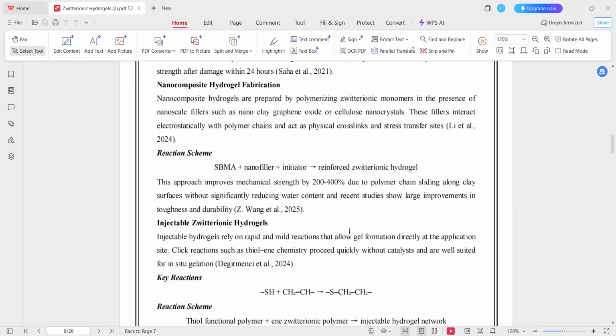The next method of synthesis is nanocomposite hydrogel fabrication. Nanocomposite zwitterionic hydrogels are fabricated by polymerizing zwitterionic monomers in the presence of nanoscale fillers such as clay nanoparticles, graphene oxide, or cellulose nanocrystals. These nanofillers interact with the polymer chains through electrostatic interactions and hydrogen bonding, acting as physical cross-linking points. The presence of nanofillers allows stress to be transferred more efficiently throughout the network. Polymer chains can slide along the surfaces of the nanofiller, which dissipates energy and increases mechanical strength without significantly reducing water content. As a result, the nanocomposite zwitterionic hydrogels often show several-fold improvements in toughness and durability compared to the neat hydrogels.